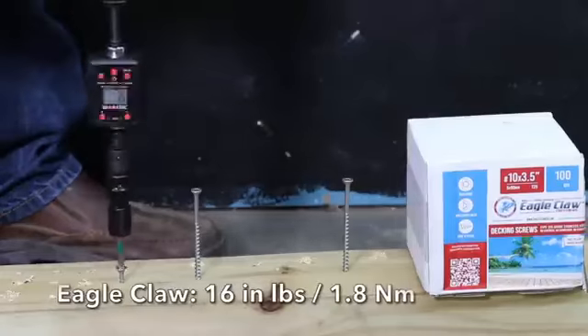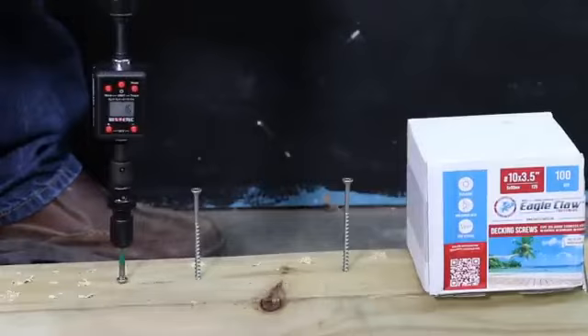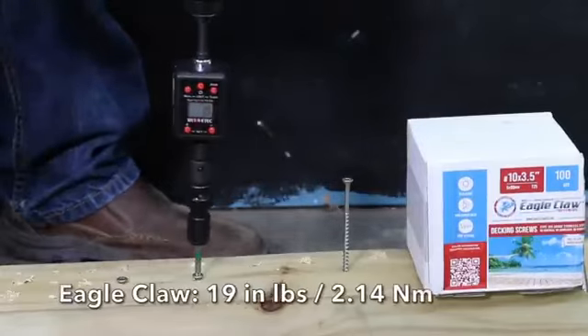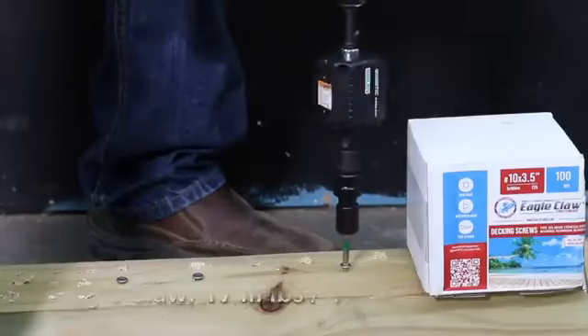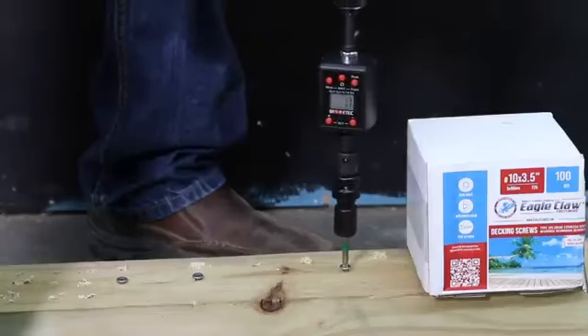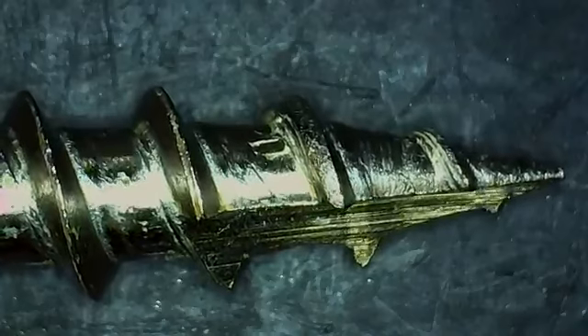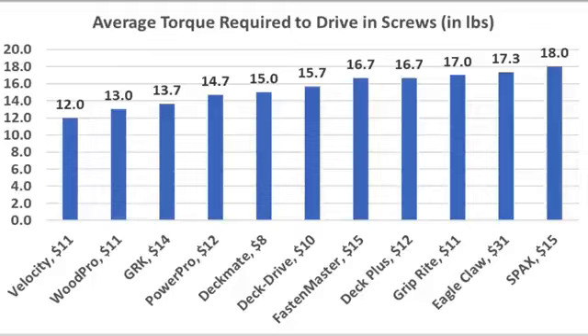The stainless steel Eagle Claws needed 16 inch-pounds on the first screw, 19 inch-pounds to drive the second screw, 17 inch-pounds on the third screw for an average of 17.3 inch-pounds. There's no coating to be damaged on the Eagle Claw. If you're looking for the screw that takes the least amount of torque to drive, the Velocity came in on top at 12 inch-pounds. WoodPro wasn't too far behind at 13, GRK 13.7, PowerPro 14.7, and Deckmate 15 inch-pounds.